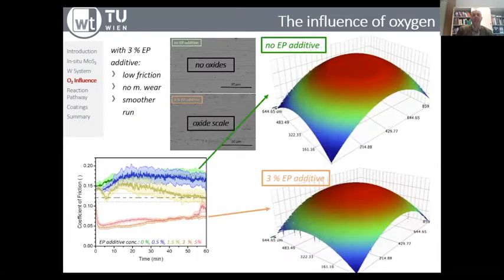Also, if you just simply look at the ball surface, the counterbody, you can see that if you don't add an EP additive, you see a severe flattening of the ball. And if you add already 3% of the EP additive, the ball surface is not flattened, there's much less wear, and we have the significant jump down in the friction coefficient.